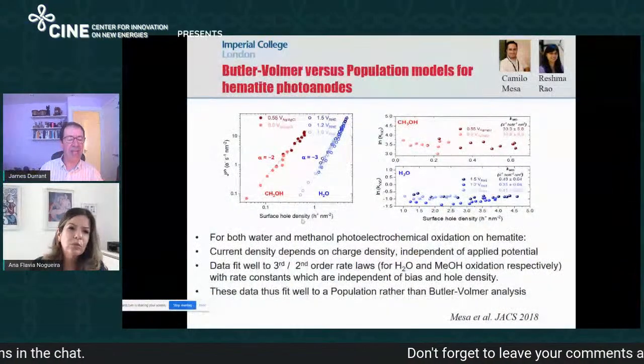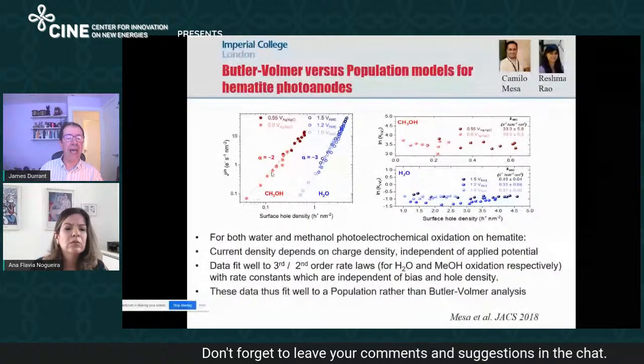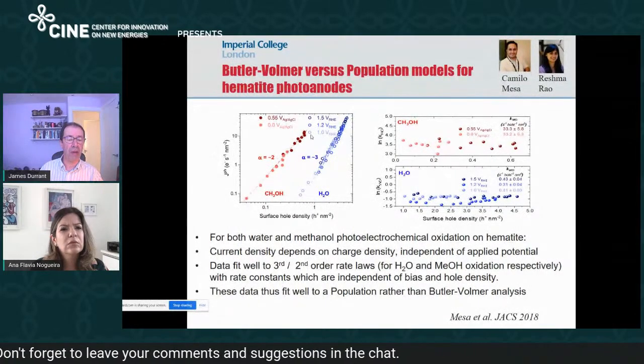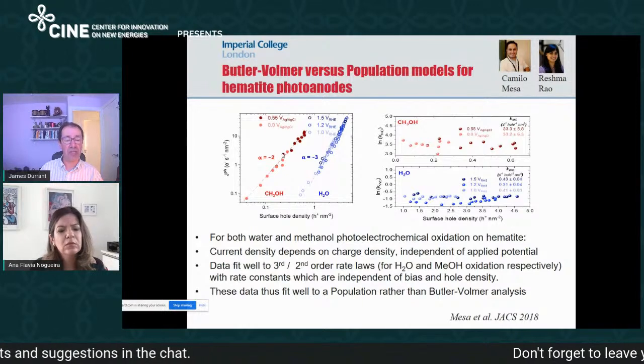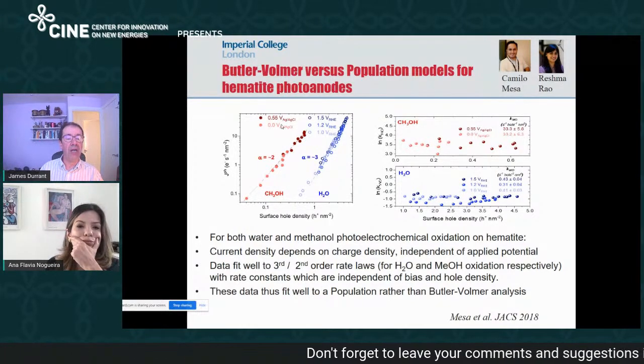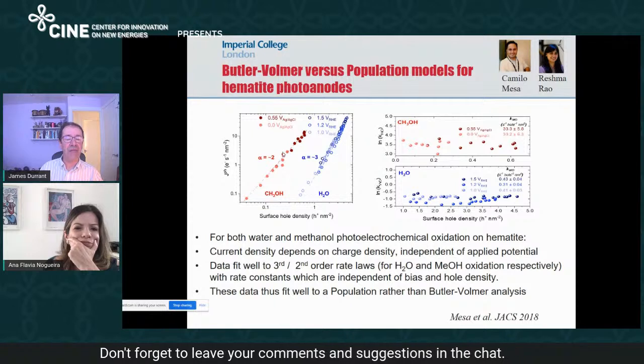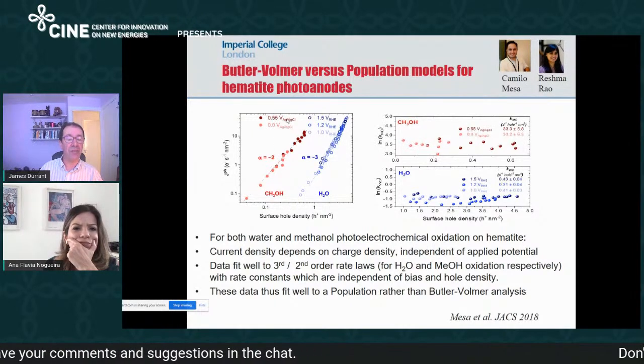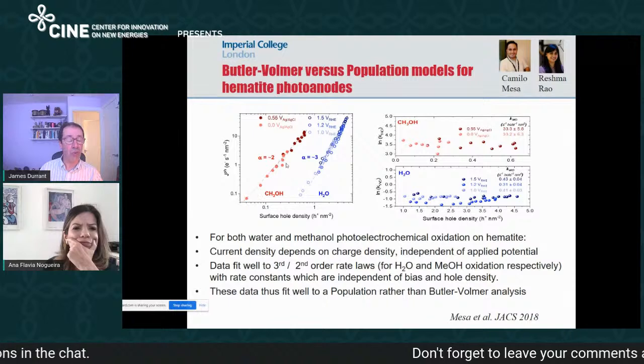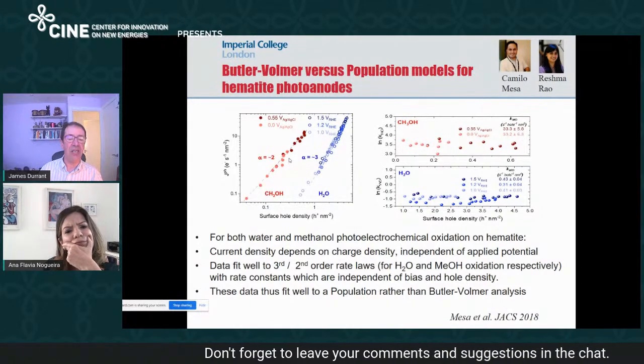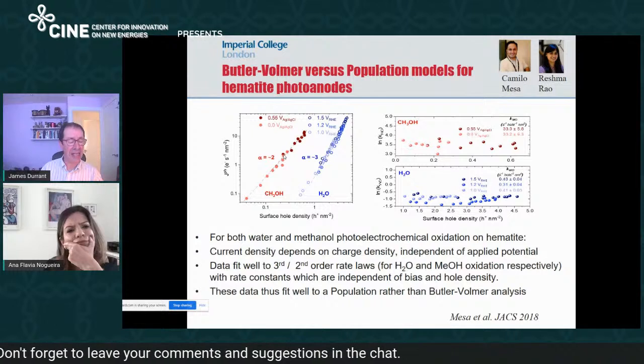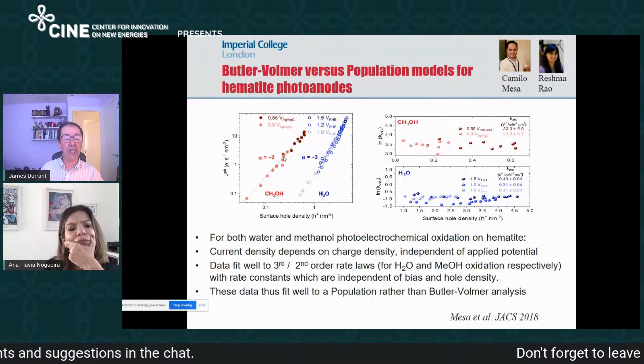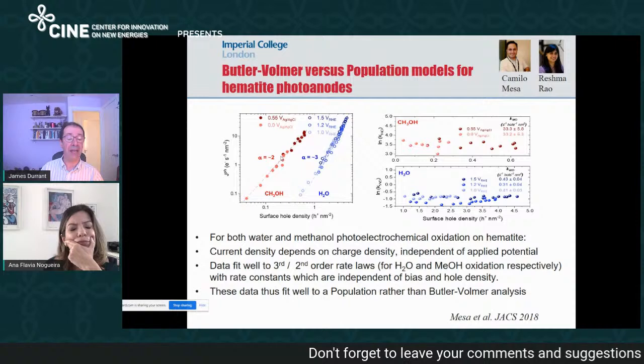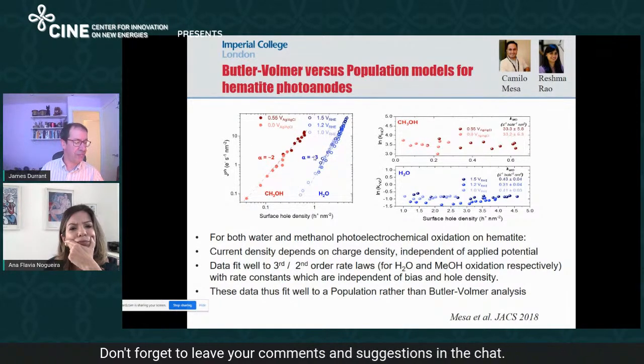So this is data here where we were showing that the potential didn't matter as long as we normalize to the same density of surface holes. If I take the pale and the dark points here, the dark points are that strong positive potential. In this case, you don't need much light to generate lots of charge. So this point down here is quite a low light intensity at that potential. At 0 volts, you need much more light because you can't separate the charge so easily. And so that point there would correspond to a high light intensity at the same potential. The point is that when you normalize to the amount of holes you ended up at, you get exactly the same flux of water oxidation.